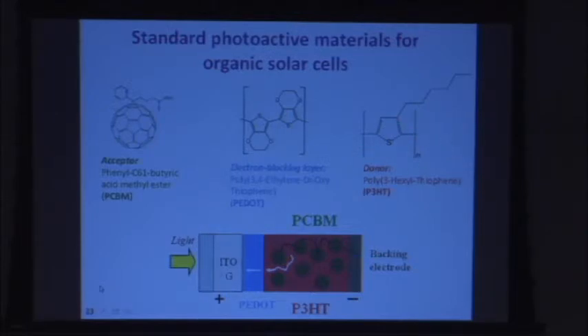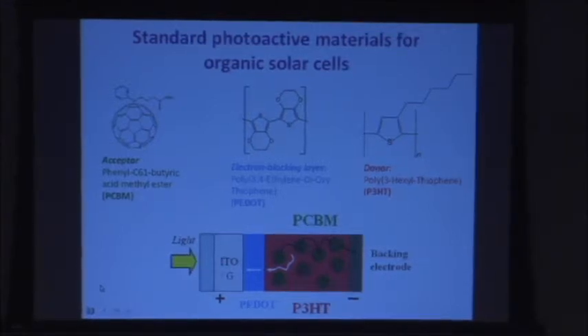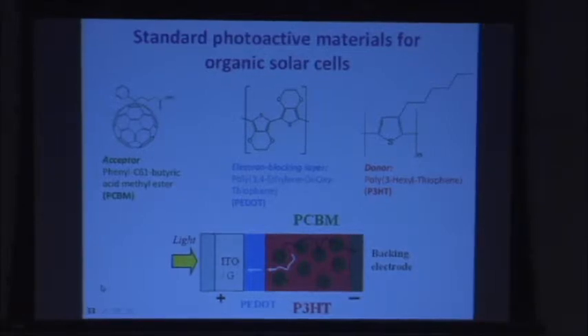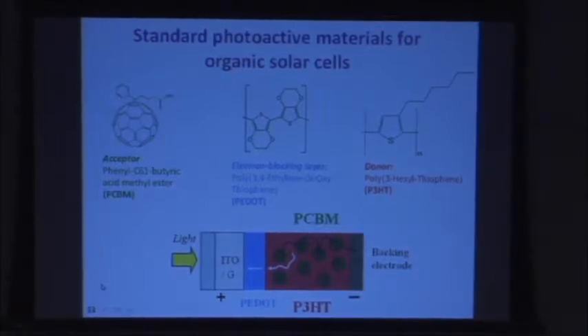For these materials, the exciton diffusion length, so if you produce in this material an electron hole pair by illuminating it, the diffusion length is very small, much shorter than in inorganic materials, for a number of reasons that are related to this curious coupling between electrons and phonons that we have seen that is responsible for the thermal conductivity of graphene, basically. So the exciton travels very little in this material.